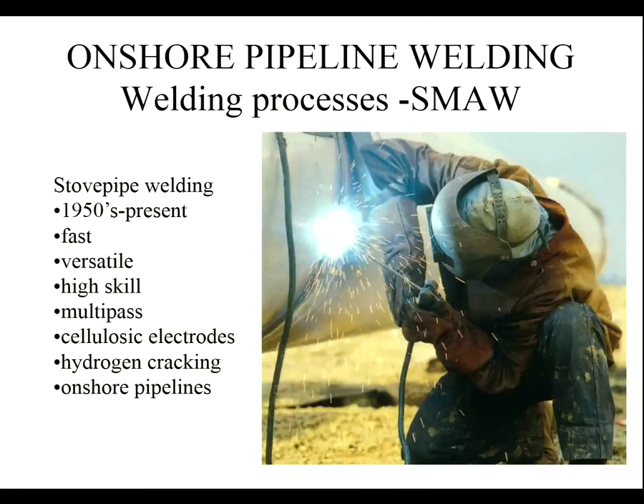So as I said, cellulosic electrodes were originally used, but that led to hydrogen cracking. And so there was a whole set of work done on preheating of the pipes to prevent that, to allow the hydrogen time to escape. And it was largely the standard for onshore pipelines and remains pretty much so today. Because site welding is being done in a field in the middle of nowhere. Offshore pipelines, as we'll see later, is done on a lay barge where the conditions are much more controlled. So you can afford to use more different welding techniques than have been done here.